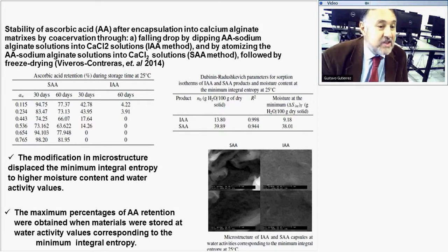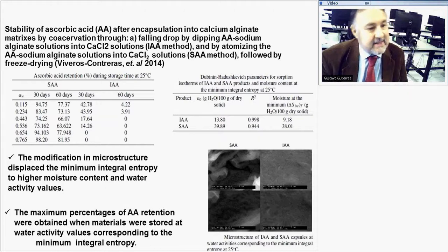And we know that this material has more active sites, and the degradation of the ascorbic acid was more pronounced there, after 30 or 60 days. Also, the glass transition shifted from 9 to 38 percent moisture content for the structure.